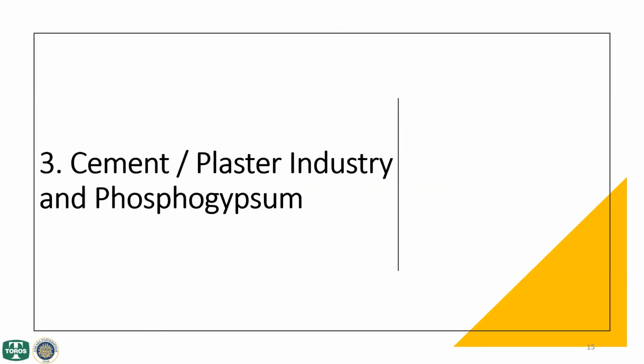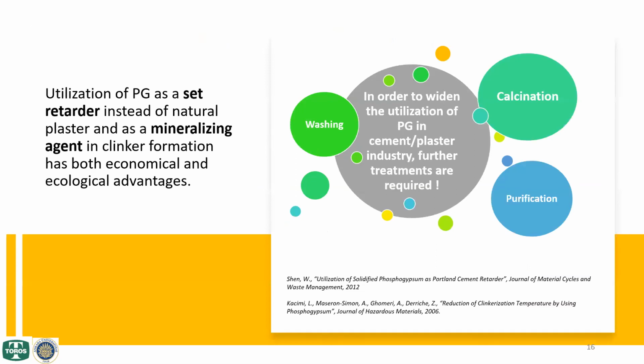So let's focus on the cement and plaster industry and phosphogypsum. New technologies, potential markets, and decreasing supply of natural gypsum enable an increase towards recycling processes of PG. Valorization of PG as construction material offers a promising solution since it allows continuous consumption of PG stacks. And there have been studies on utilization of PG as a substitute for natural gypsum in the production of Portland cement to control the hydration rate and retard the setting time.